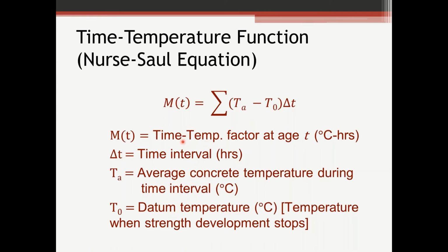So this is your time temperature factor at age t. Delta T is your time interval in hours. You're measuring temperatures typically every half an hour, sometimes every 15 minutes. But T sub A is the average concrete temperature during that delta T time interval, so during that 15 minutes or half an hour, 1 hour, whatever your interval is. And T sub 0 is the datum temperature, which is the temperature at which strength development stops. Most of this is all in Celsius.